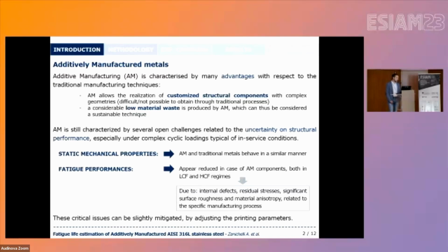For example, relative to the fatigue performance of AM components, it appears to be reduced with respect to the corresponding traditional metals, both in low and high cycle fatigue regimes. And this is mainly due to the internal defects, the residual stress, the surface roughness, and the material anisotropy that are all related to the specific manufacturing process.